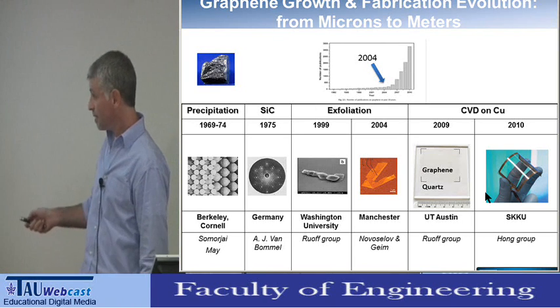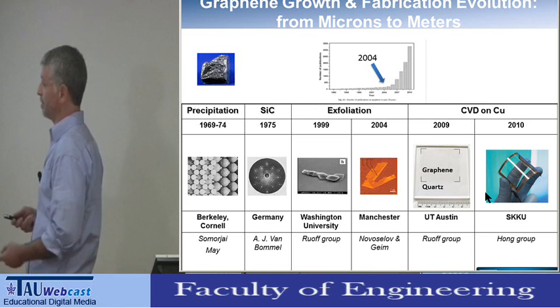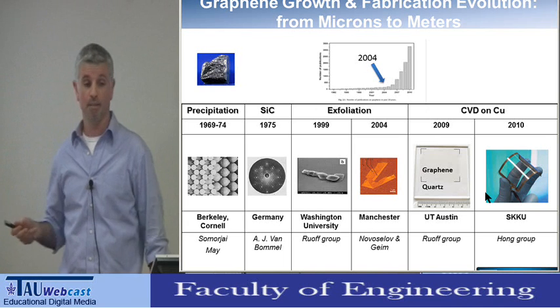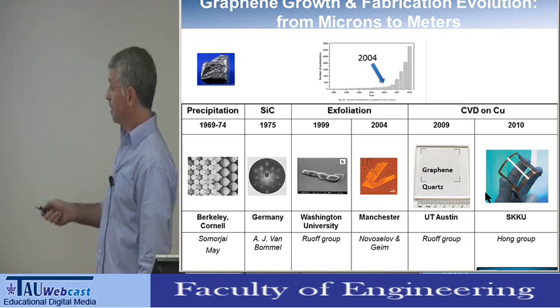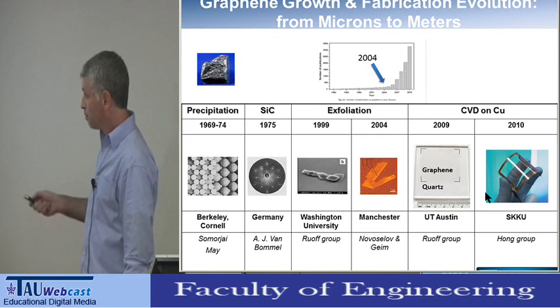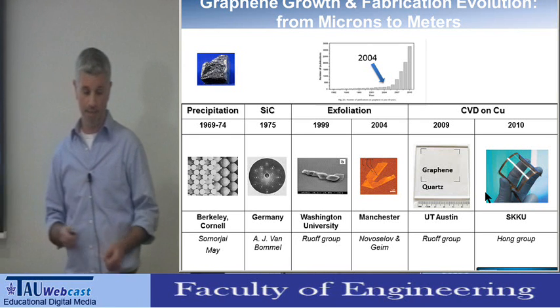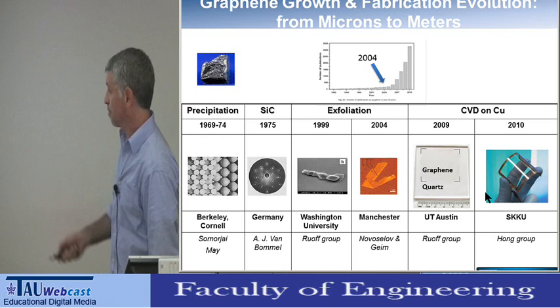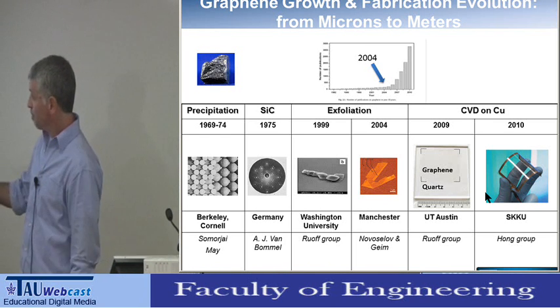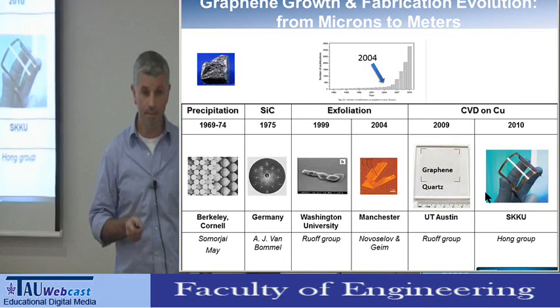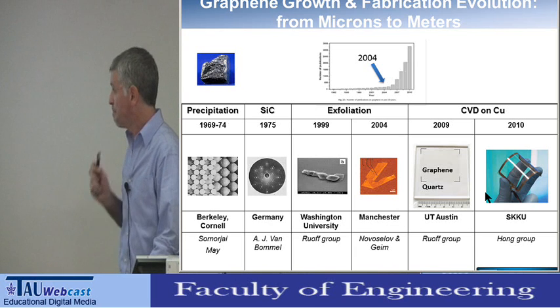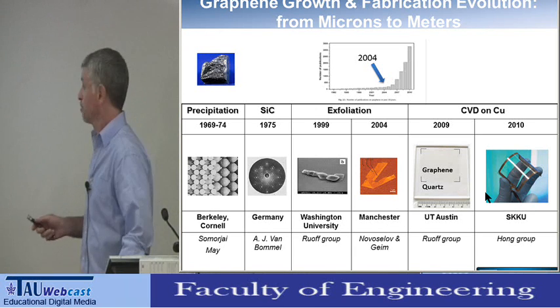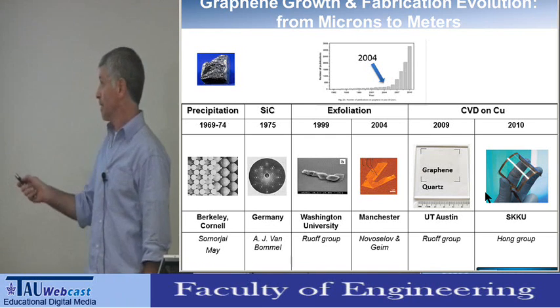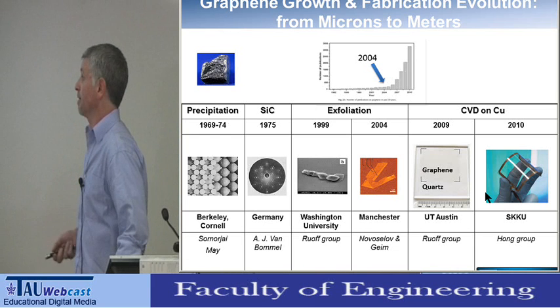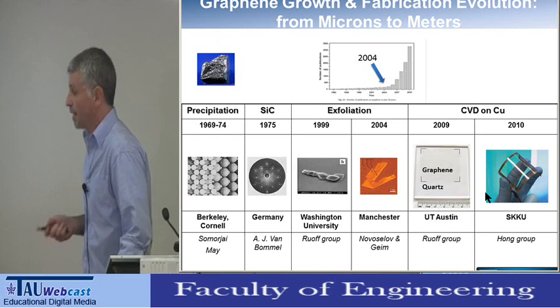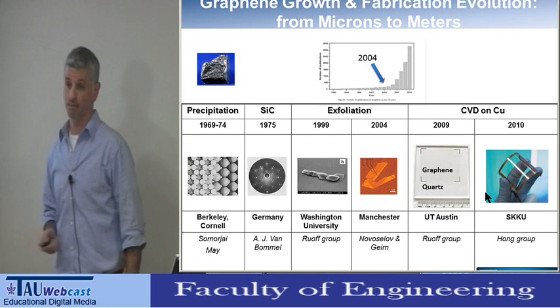In the early 70s, graphene was identified to appear as a single layer on single crystal transition metals by May from Cornell, then on silicon carbide. Then it was attempted to isolate it by different mechanical exfoliation techniques. And then the Manchester group did their work in 2004. But then it took 5 years to find a way to synthesize, in a consistent manner, single layer graphene over large areas. And actually, only today can we grow single layer graphene with electrical and physical properties comparable to the exfoliated graphene.